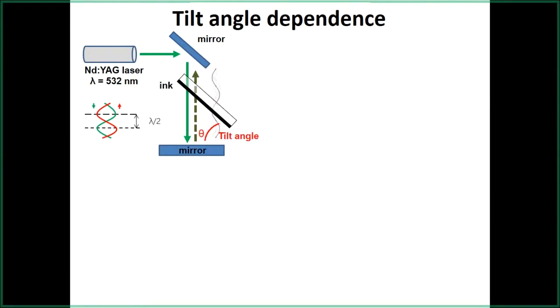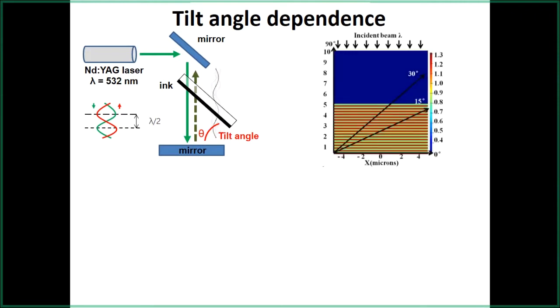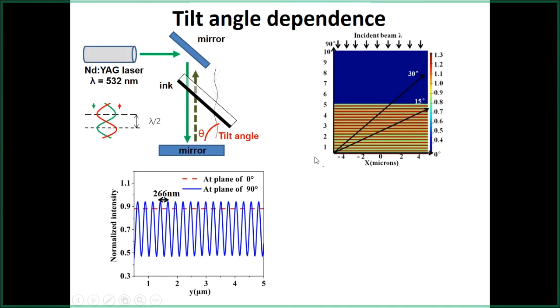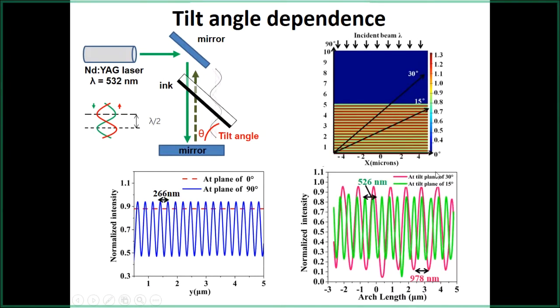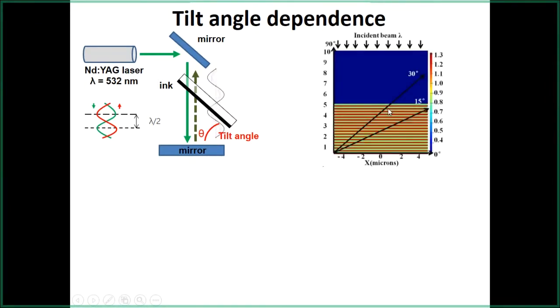A bit of simulation: what about the dimensions of the gratings that we produce? This is a simple simulation that simulates an incident beam coming from the top and then reflected from the bottom. You have a standing wave, and if you put your glass slide at different angles in the standing wave, these are the graphs. So what you see is at different angles, for example, at 30 degrees, you have the pink graph, and at 15 degrees, you have another graph. You can change the periodicity of the grating that is produced just by changing the tilt angle. And here is the demonstration of that.